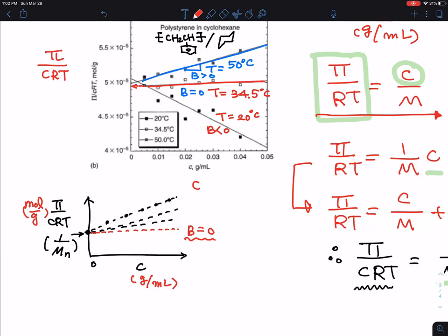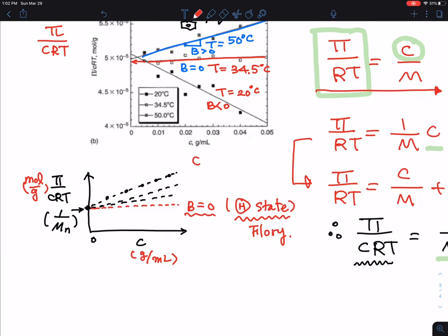Your concentration change, whether you put polymers or not, there is no rise in osmotic pressure more than just linearly proportional. In polymer cases, this is called the theta state. This is the term by Flory - theta state temperature by Professor Paul Flory. This is a theta state where essentially polymer chains and solvent chains do not discriminate each other. That's a very important thermodynamic state in solution where polymer chains have the same size as in the melt state.